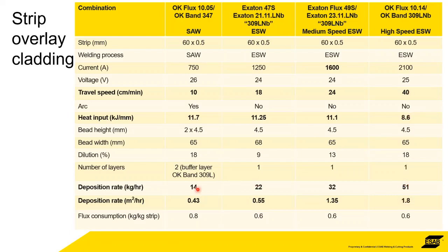If you remember right at the start, we're talking 14, but that's in effect halved, so that's 7 up to 51. It's absolutely huge. Okay, you can achieve it in a single layer, but you need 2100 amps. So it's a big power supply. Okay, but we're talking about maximizing what's available.